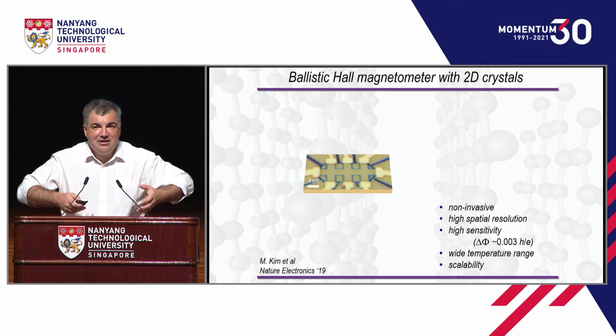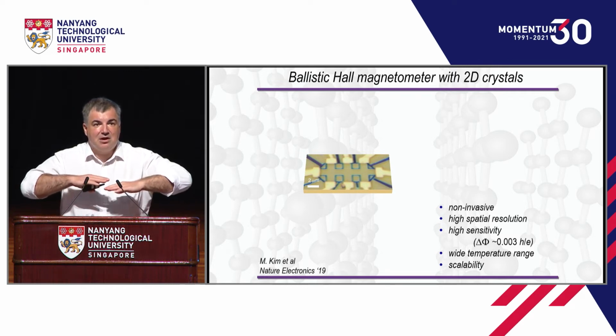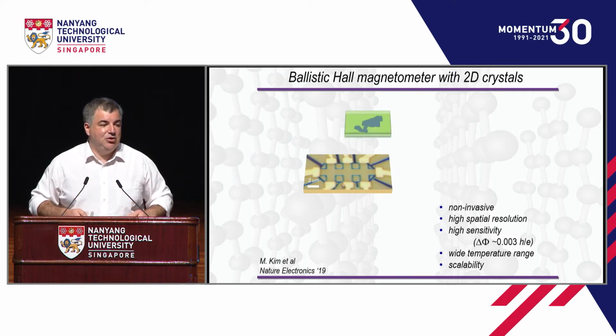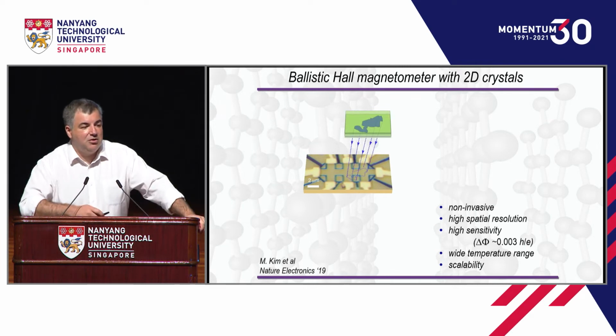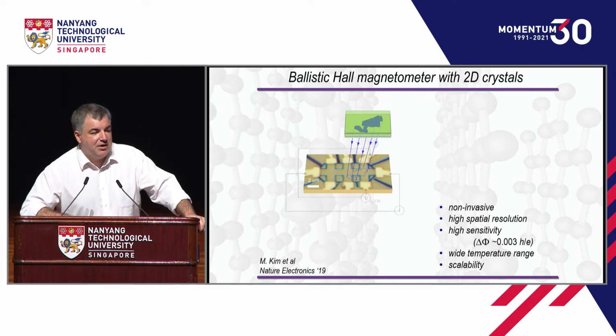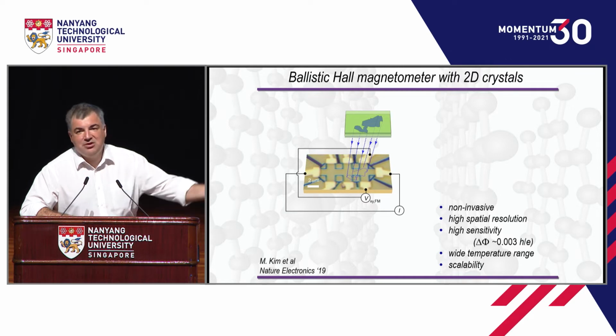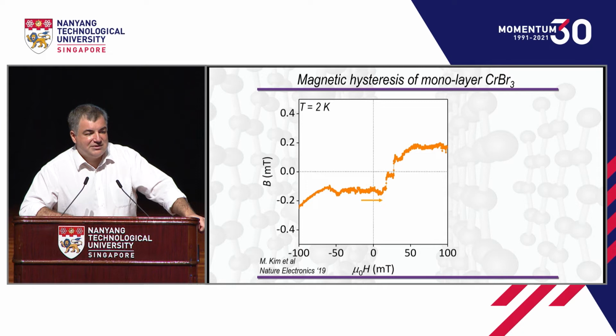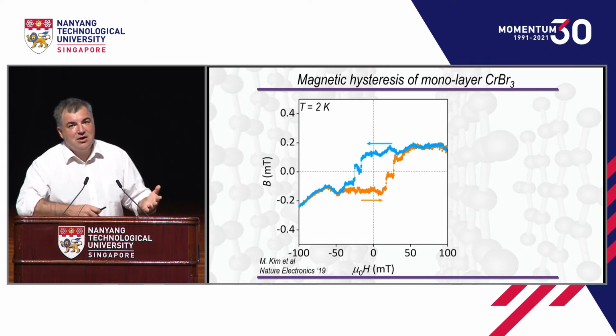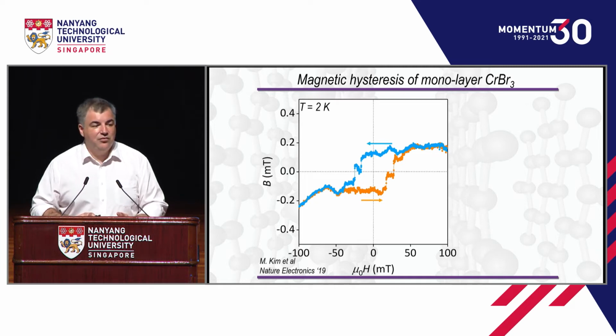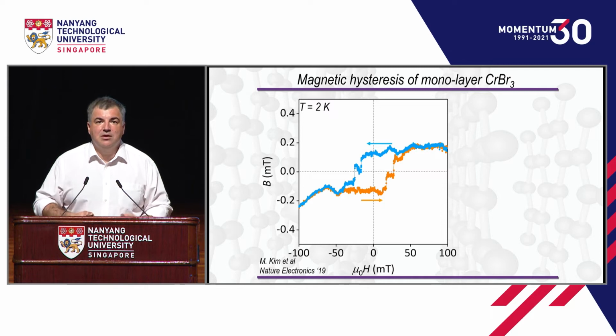So you just create this stack with the graphene Hall sensor, and then you bring your ferromagnetic material and you place it on top. Then you just send current and measure voltage. Very simple behavior, and that's the magnetization of this material. So if you go at low enough temperature, it starts to be ferromagnetic.